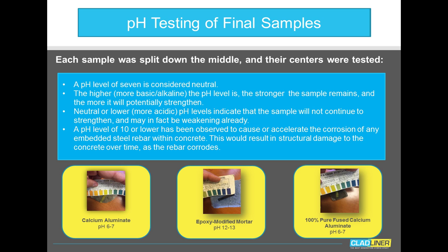So when we look at those samples that we had, we split each one of them down the middle, and in their centers we tested the pH. So the calcium aluminate had a pH of between 6 and 7. Again, this would be kind of just below neutral, so it's already beginning to weaken potentially. The epoxy modified mortar, the pH was between 12 and 13, which is really good, really high, which means not only is it very strong, but it's still protecting any rebar that might be embedded in there.